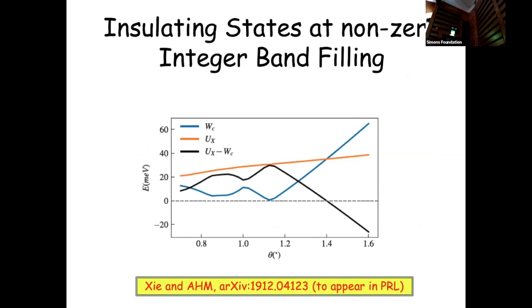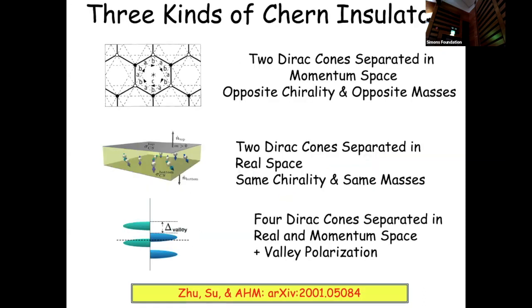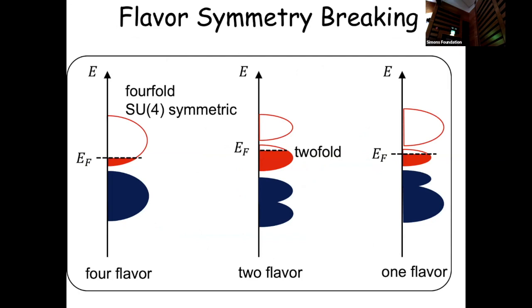So having those splittings between the bands, like spin splitting in a Néel system, if you like, is something that can only happen if the bands are flat enough compared to the strengths of the interactions. And so you can estimate that this occurs over some range of interaction angle, actually where this black line is positive. And so all of that seems to be pretty well understood.